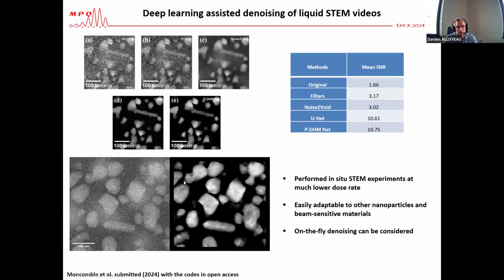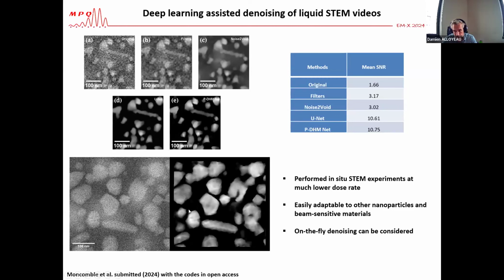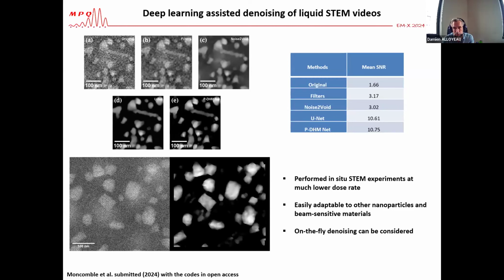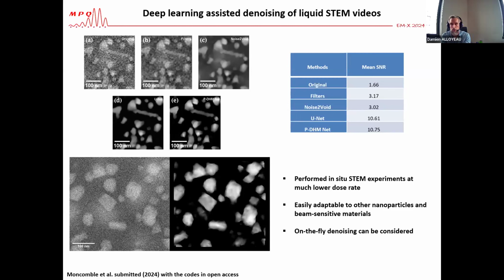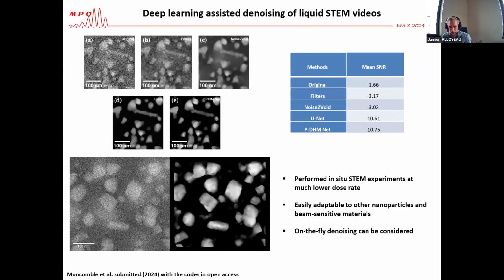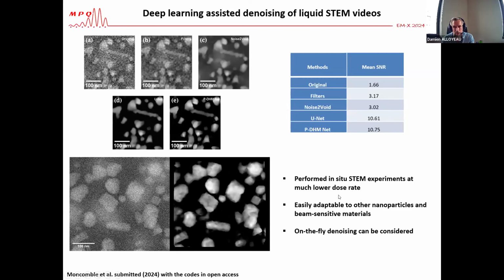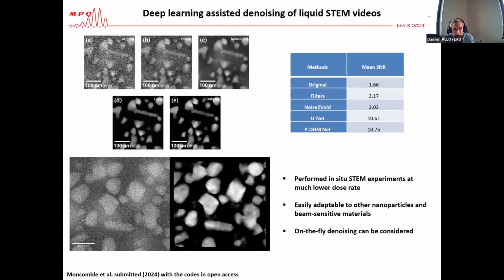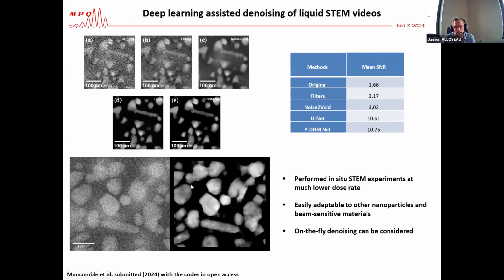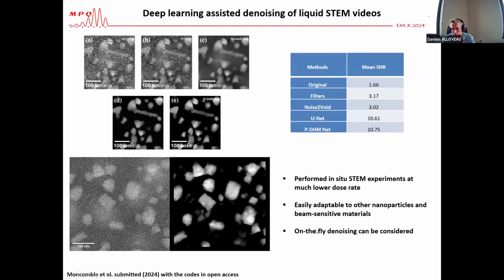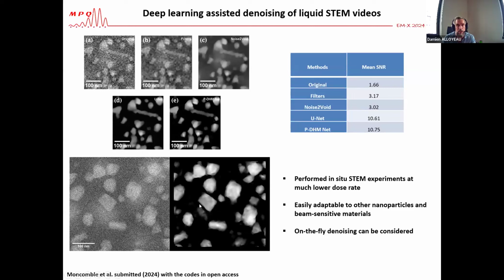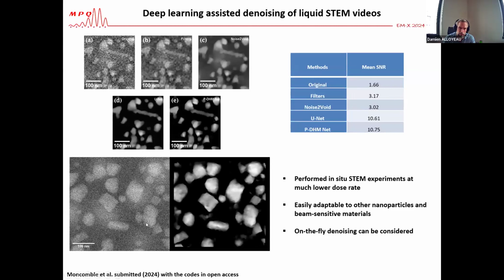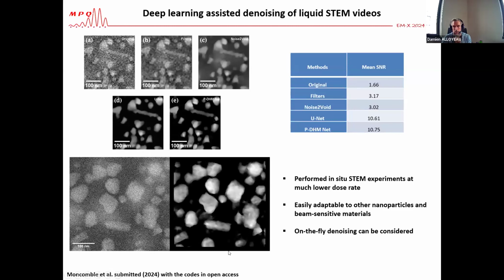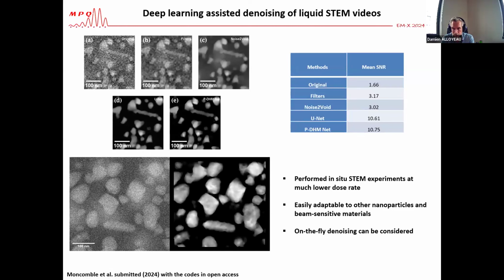And what is very interesting here is that it also works on videos. So it gives us the possibility to perform in situ STEM experiments at much lower dose rate, because now we can improve the contrast of nanoparticles after the experiment. It's very easily adaptable to other particles and beam-sensitive materials. It takes only a few hours to train the network with a new set of samples. And once you have trained your network, it's extremely fast. So we can now consider on-the-fly denoising to obtain this type of image directly on the microscope. This will be out soon in the articles of Adrien, and all the code will be in open access to allow the community to benefit from these new deep learning assisted denoising methods.